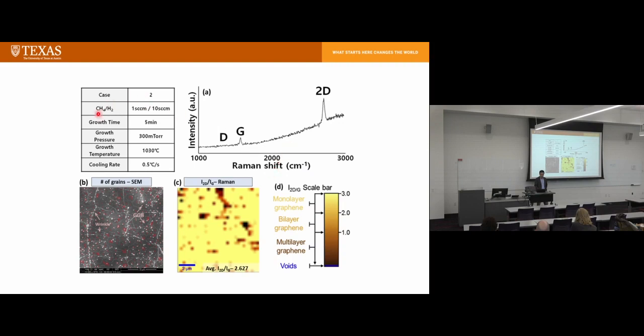Now you control the gas concentration between methane and hydrogen, and control growth time, growth pressure, growth temperature, and cooling rate. Those are regular growth parameters. And you use Raman mapping to detect graphene. Usually you're looking at the G peak and 2D peak. If the ratio is above 2, then you know there's monolayer graphene. That's the goal we shoot for. We want to have monolayer graphene. And you can use Raman mapping to figure out if the growth is high quality, large scale, large area.